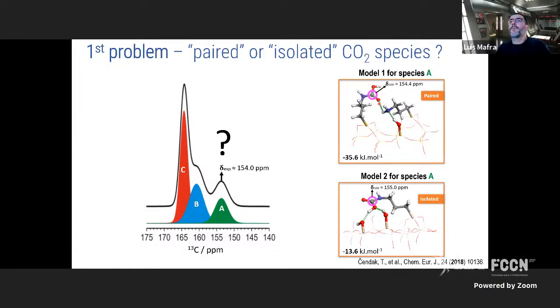There's still a problem. What is this peak? Hey, you know, in 2011, I showed you the first work we have done. We only saw 2 peaks, carbamic acid and another one, which we think is the ion pairs, carbamate. But when we control the environment, when we pack the sample, we always have an additional peak that we label here A from now on. And this was very puzzling.